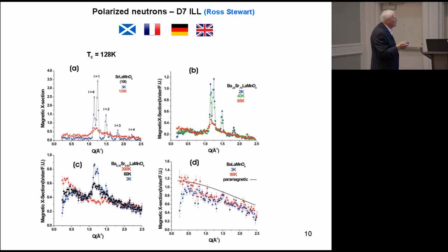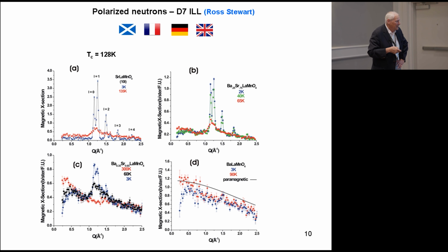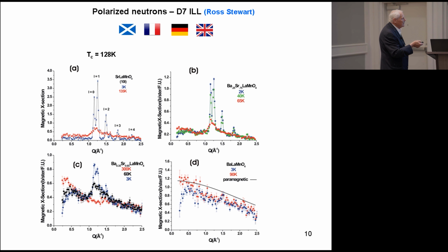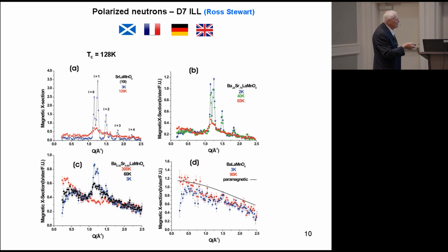And you can see that when you get above the Néel temperature, 128, you start seeing these very funny line shapes. And these funny line shapes persist all the way to the all-barium case, where we substituted all of the strontium with barium. And we don't see anything at all. The magnetic cross-section is in fact relatively featureless. It's practically paramagnetic in this sense.